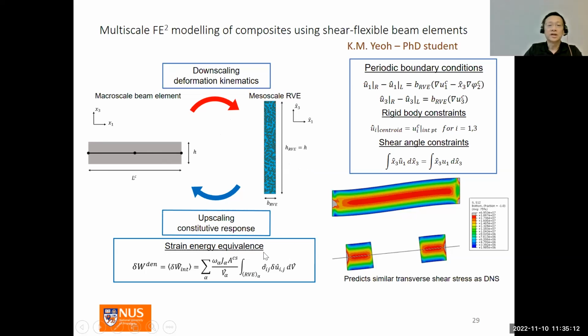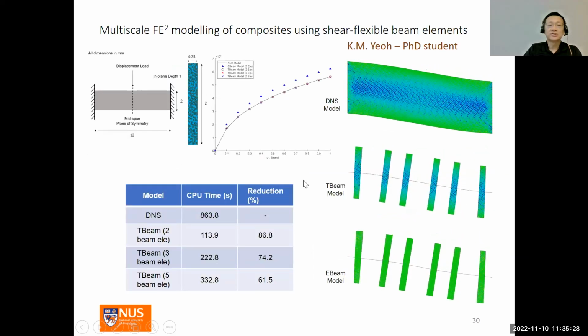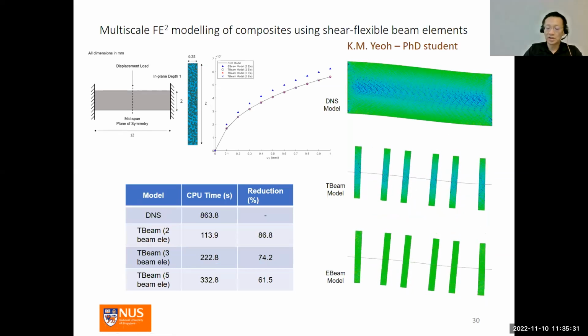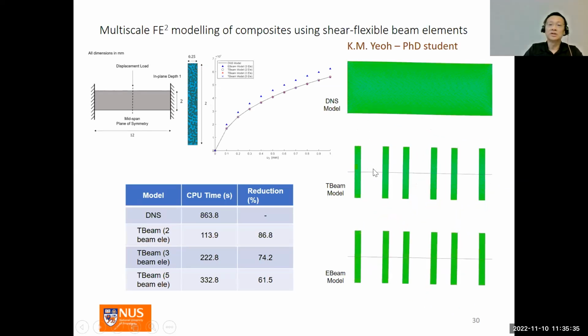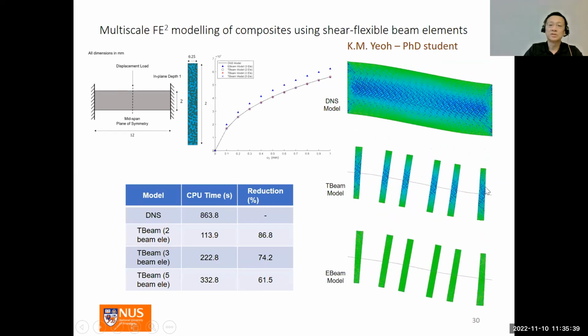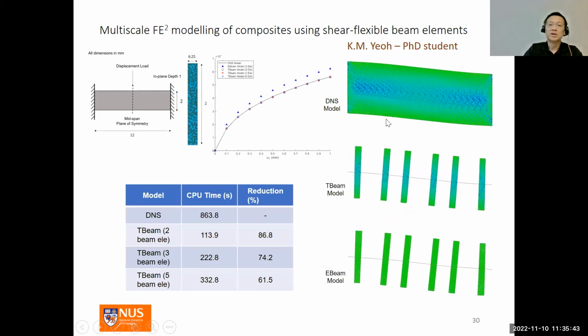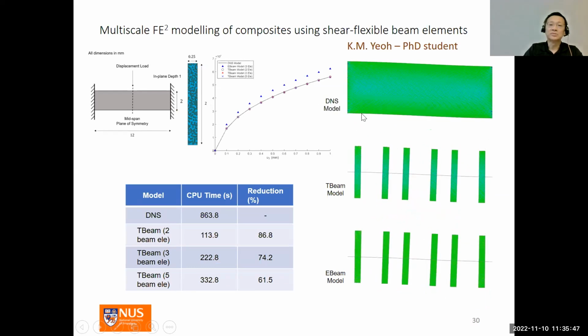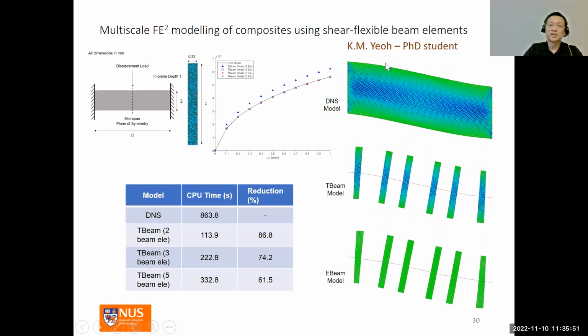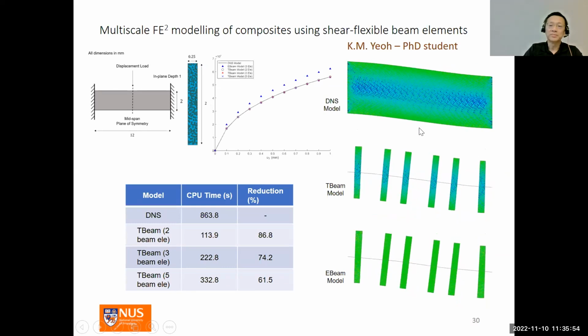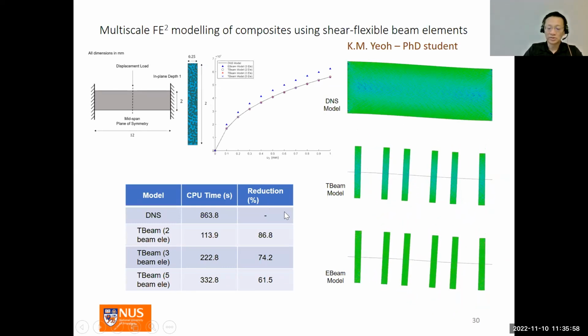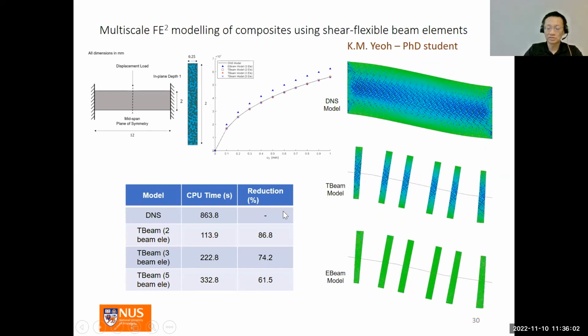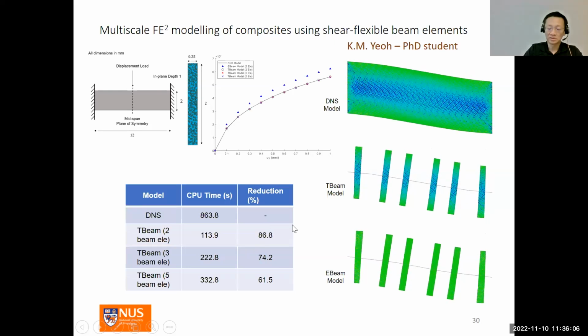Here we have the strain energy equivalence. This is the scaling factor that has to be applied to the RVE. So this is the magic sauce that I mentioned just now. This animation shows that the deformation of the direct FE square model is similar, and the stresses are similar to that of the direct numerical solution model, which is basically just a very large finite element model of the whole beam. And it's possible to show savings in computational time compared to the DNS model as well.